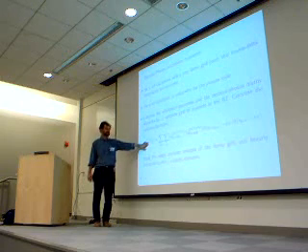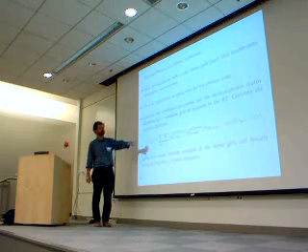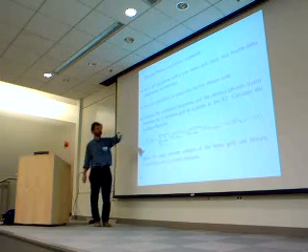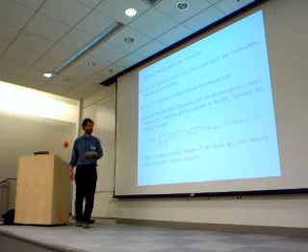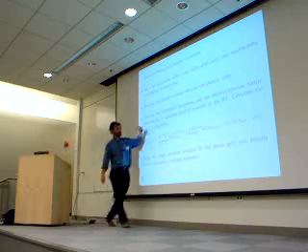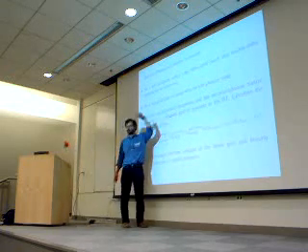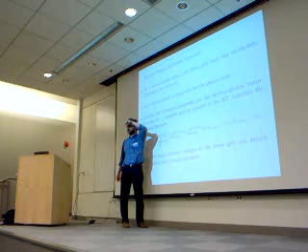So by calculating this object, one can Fourier interpolate it to any q point in the Brillouin zone, and then for every point in the Brillouin zone where you are interested, you similarly have the Fourier interpolated dynamical matrix.